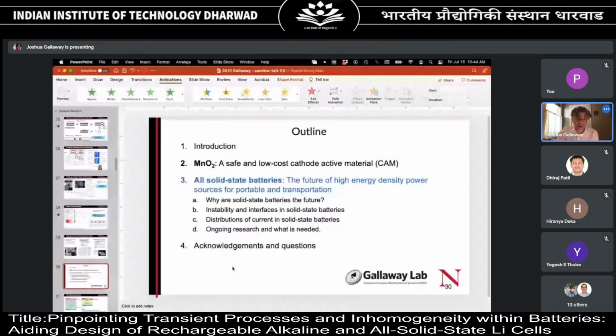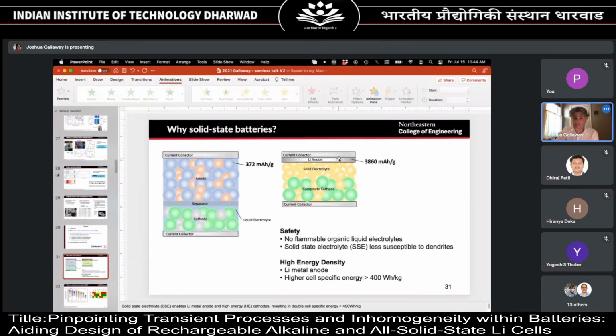So here's a schematic of a typical lithium-ion battery, where you have a relatively big anode coupled to the cathode. And if we replace the liquid electrolyte with a solid electrolyte, we may be able to replace this anode with a simple foil of lithium. So here we have just a small foil of lithium that's replacing this big anode. And that's made possible by the solid electrolyte. So you see here the two schematics. The solid state one is smaller. So that shows the concept of making a battery smaller by using a solid electrolyte.